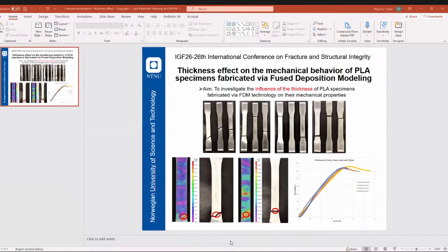The reason behind this is due to the following reasons. First is because of the first layer quality. The other is that, because of the increase in the thickness, there is a higher temperature gradient in the layers, which can result in an increase in the diffusion process. So we also decrease the void ratio and improve the strength of the bonding process.